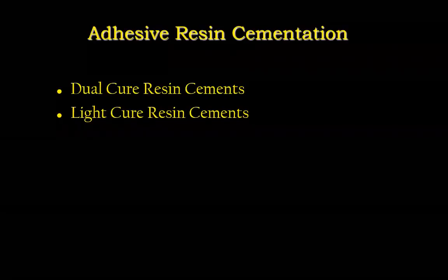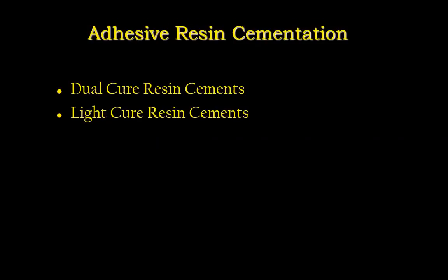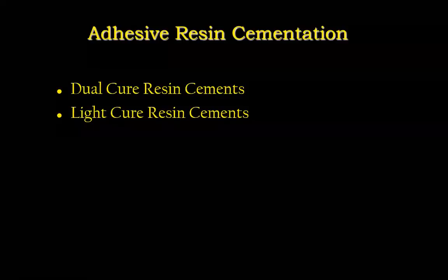But with a dual cure resin, it's different because you've got facial margin, lingual margin, you got interproximal margins when you're doing a full crown. So it's easier for me to clean off in a gel state. But what I do is I want to initiate that gel state by shining the light. I polymerize with the light for just 1 to 2 seconds. I go 1001, 1002, boom, my light goes off. What it does is that excess cement that's oozed out when you seat your crown, it will get in a gel state, but you don't want to go too long. If it gets too hard, it's much harder to clean off.